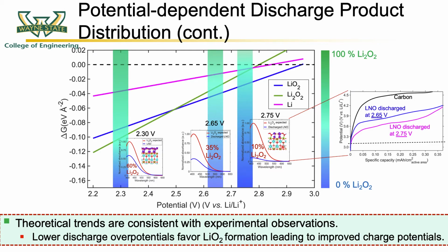It is observed that when a cell is discharged at a constant potential of 2.75 volts and then charged back up, a further reduction in the charge overpotential is observed as compared to a cell discharged at 2.65 volts.